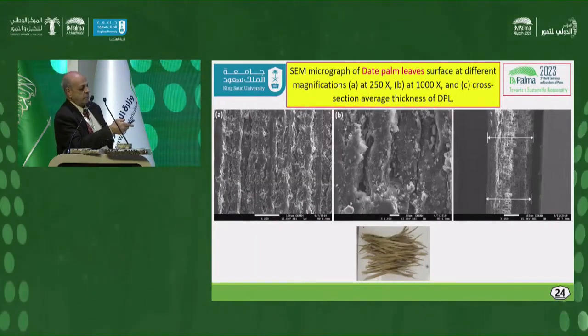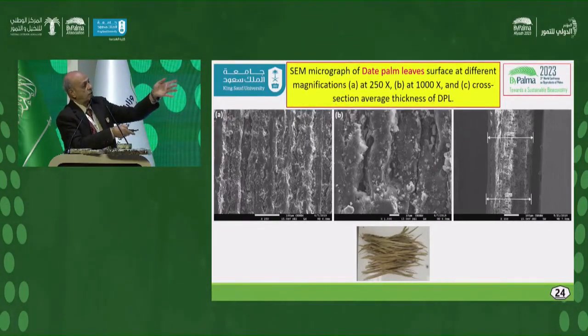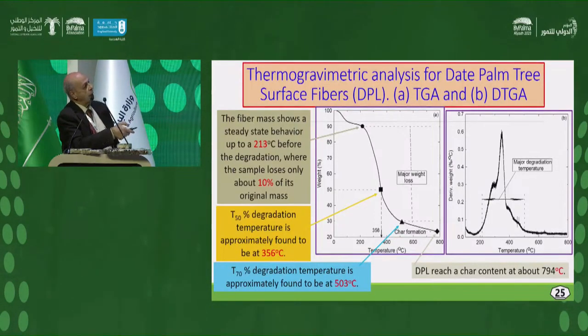This is the SEM of the date palm leaves, okay? And this is the thickness of the leaves. This is the TGA for that. It also shows that the date palm leaf is stable up to 213. It only loses 10%, and the 50% degradation occurred at 356, okay?